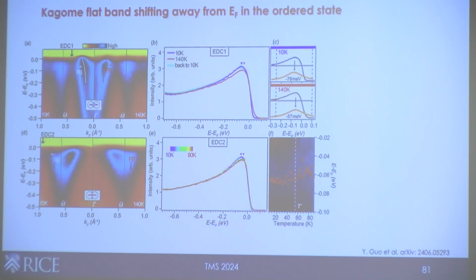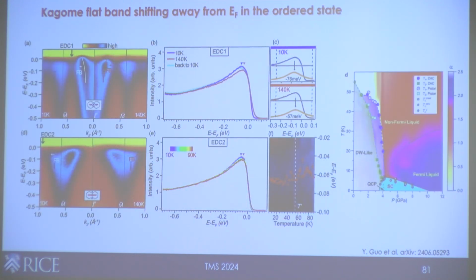And so we can further compare across the ordering temperature of 55 Kelvin, across this transition, and we can look at the position of the flat band. So as you go down from the red to blue, you can see the flat band actually shifts away from the Fermi level. We've done thermal cycling to check that this is a robust result.